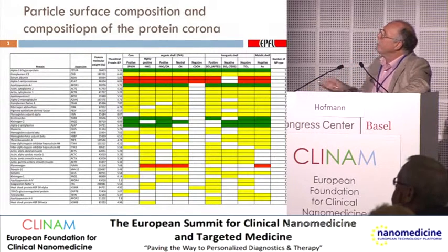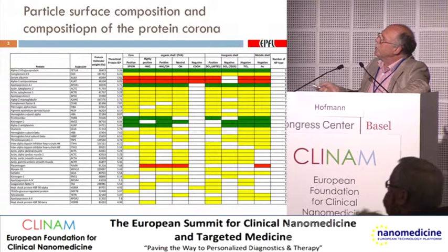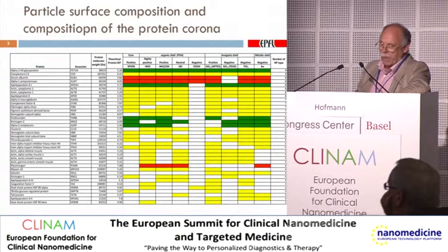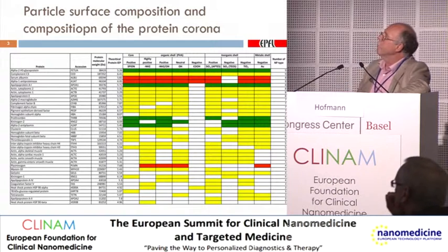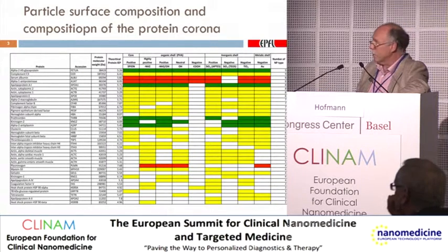And if you go now to the inorganic coating of the particle, we have here positive and negative charge, and both are silica, but with different functional groups on the surface. You see here again a negative charge, similar negative charge, but this is silica, this is polymer. We have a different response of the particle to the media. And then if you go to titanium and gold, again, it's different. So this is a very complex picture, and it's very difficult to understand this in detail.